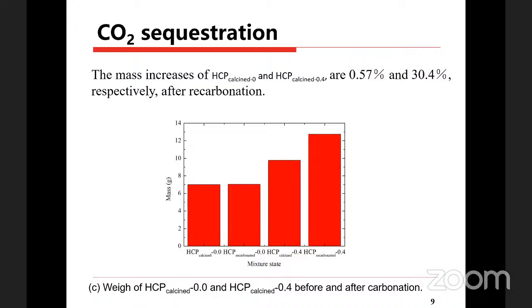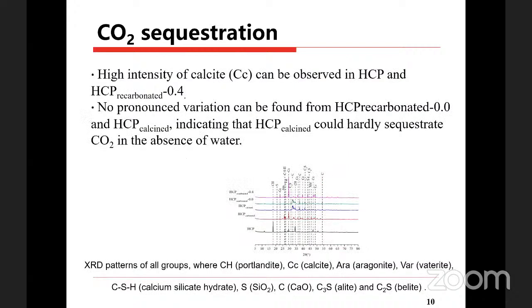And for the recarbonation process, the recarbonation efficiency is quite high if we use some water during the recarbonation process. We find a very high intensity of calcite. I think this is already reported in a lot of studies. The calcite can be observed in the recarbonated powders with water added. But no pronounced variation can be found in the carbonated powders without any water added, indicating the importance of water to sequester the CO2.